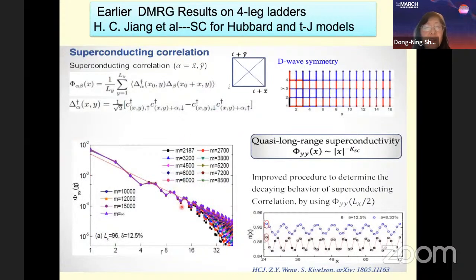One thing we need to pay attention to is that in such systems, the numerical results actually depend on the bond dimension. When we take a small bond dimension, the truncation error will make the correlations decay exponentially. Only with the increase of bond dimension can the correlation demonstrate a power law behavior, indicating quasi long-range order. So the earlier numerical studies focused on four-leg ladders, which indicated d-wave superconductivity.